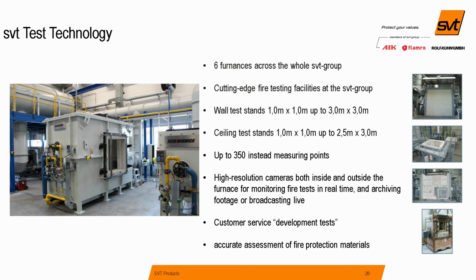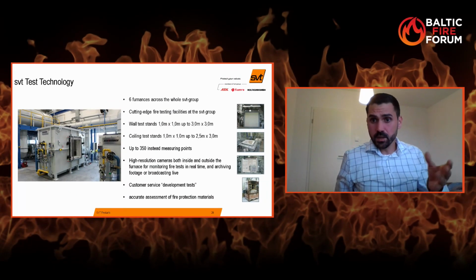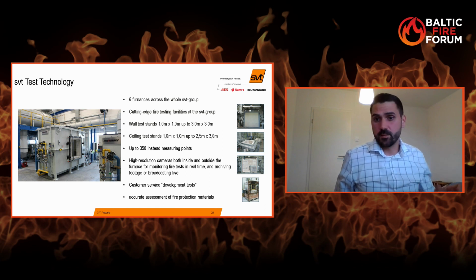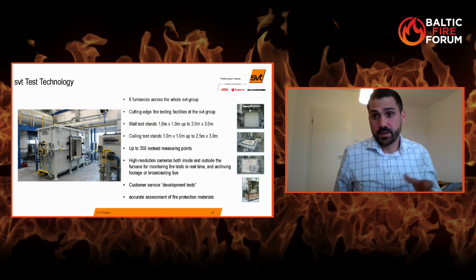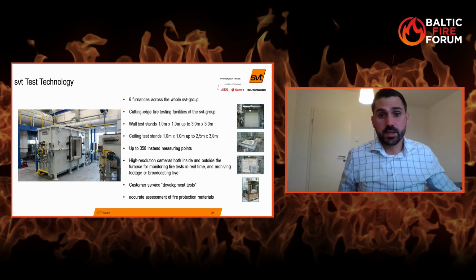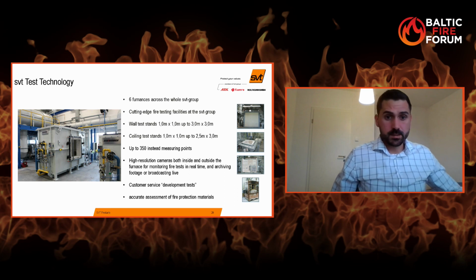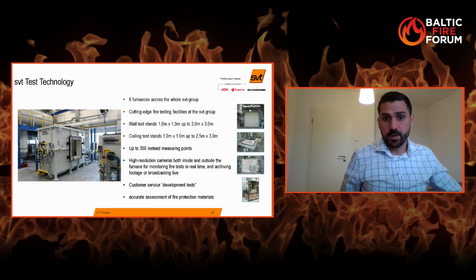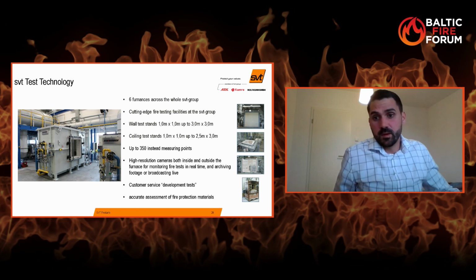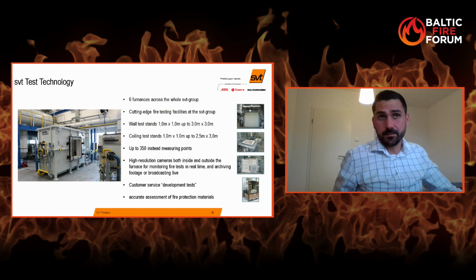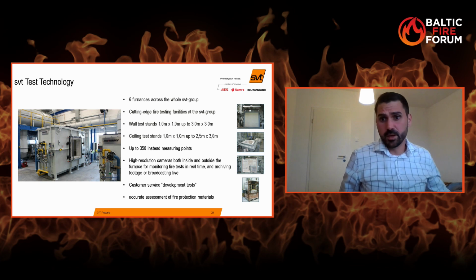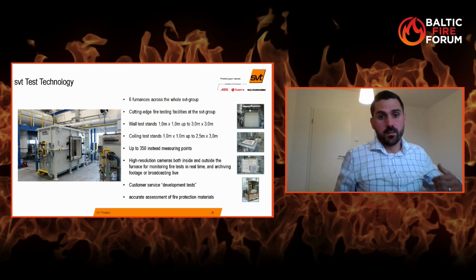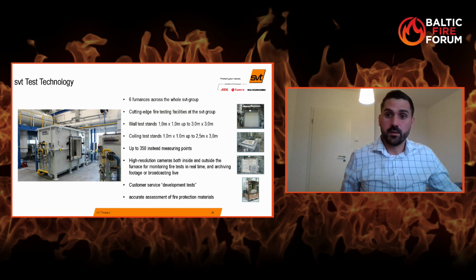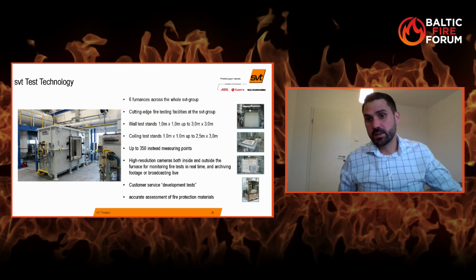But we got these furnaces to do some other oriented fire tests, made, for example, for cabinets or storage and transport boxes. You can use the furnace to check the construction of the sidewalls, for example, if you achieve your fire protection goal of 30, 60, or 90 minutes. We have a large-scale fire test with an opening of up to 3 by 3 meters, where you can install up to 350 measuring points. For us, it's our customer service to do these development tests, also with our patented battery solution, and it's all customer oriented. We get the samples from our customers, test them, and tell them, okay, you can pass the test, or you won't pass the test.